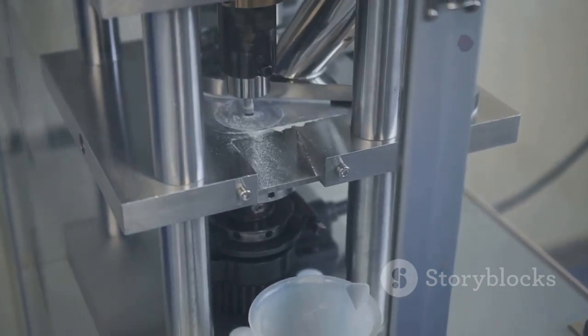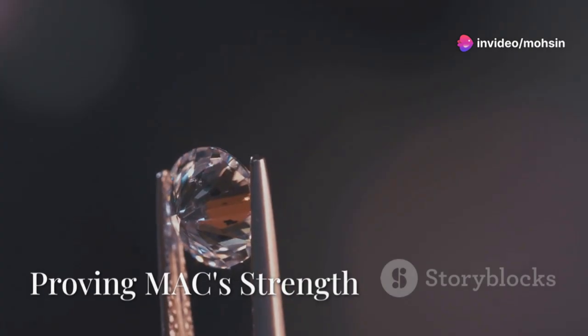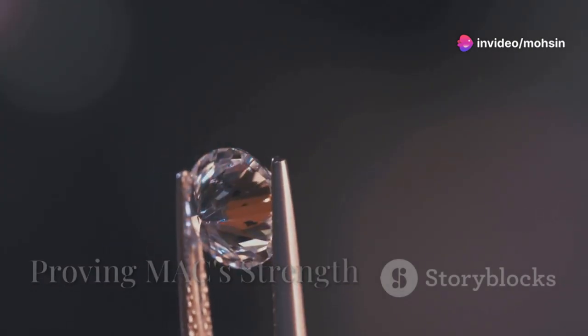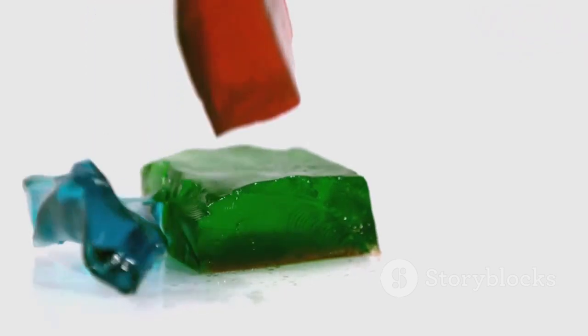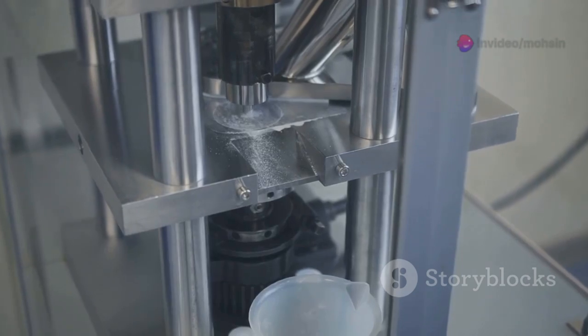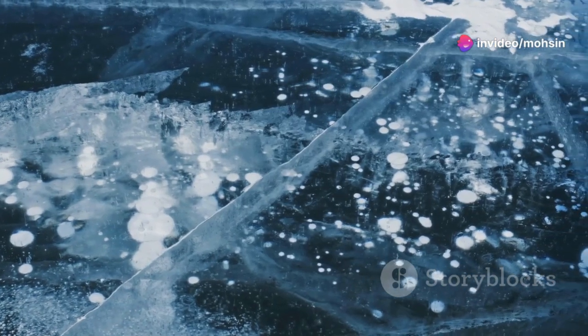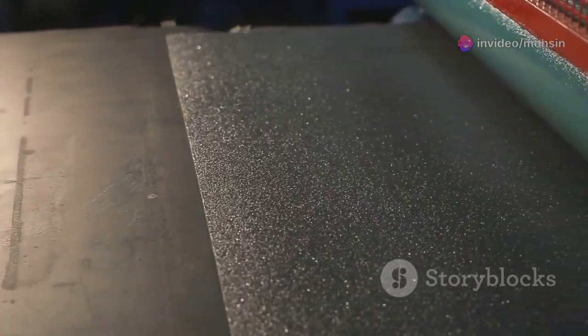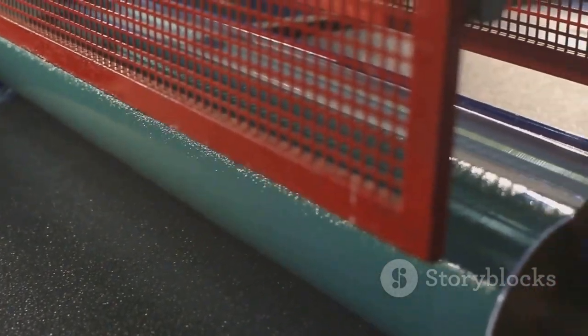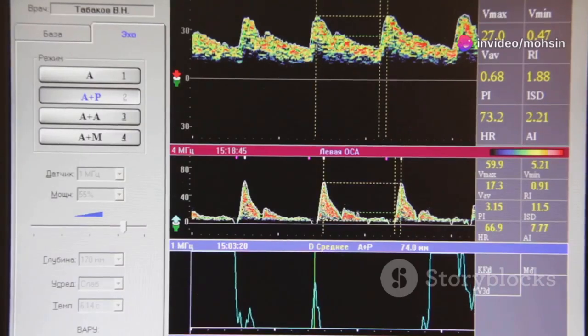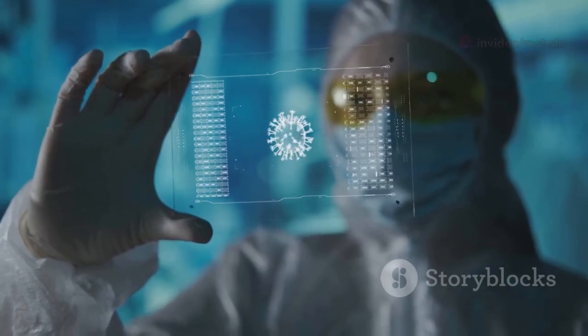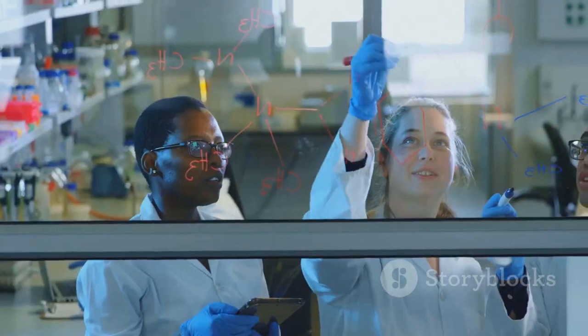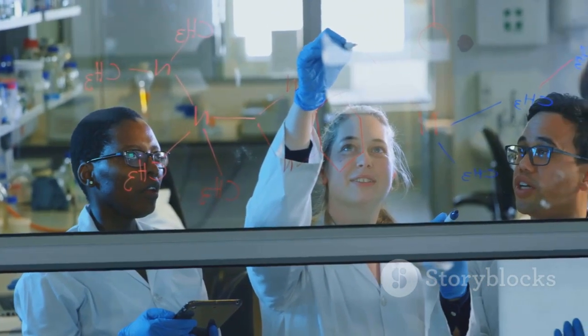This breakthrough wouldn't be possible without patience and precision. Now, with MAC in hand, the next step was to test its strength. How tough is it really? To test MAC's strength, scientists used a diamond-tipped indenter, like poking a trampoline with a microscopic needle. They measured how much force the material could take and how much it stretched before breaking. Graphene failed quickly when a crack formed, confirming its brittleness. MAC, on the other hand, stretched and absorbed energy, and even when punctured, the tear didn't spread. Its disordered structure stopped cracks in their tracks. The result: MAC's fracture toughness is about eight times higher than graphene's. Computer simulations confirmed these findings, revealing why MAC's messy structure is so resilient. This was the wow moment—MAC had overcome graphene's biggest weakness.